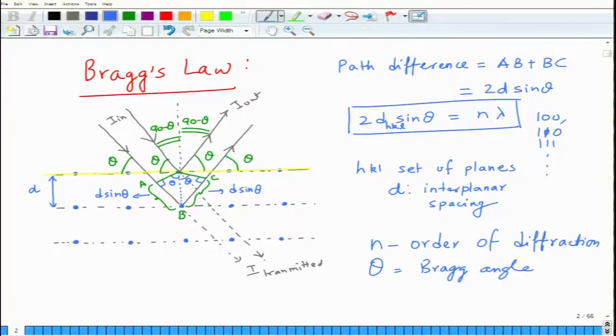So which means if your d is fixed, theta is fixed. That means diffraction cannot occur at any random angle. It can only happen at those angles at which this equation is satisfied. So that is why there is a fundamental difference between diffraction and reflection. Although it looks like reflection, it is not reflection, it is diffraction, which satisfies the Bragg's law, whereas reflection can occur at any angle. Secondly, reflection is only a surface effect. Diffraction is a subsurface effect. The information from the surface, below the surface, also comes out, okay?